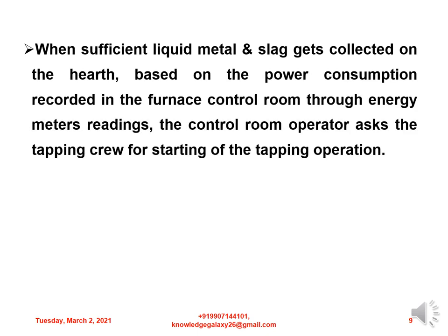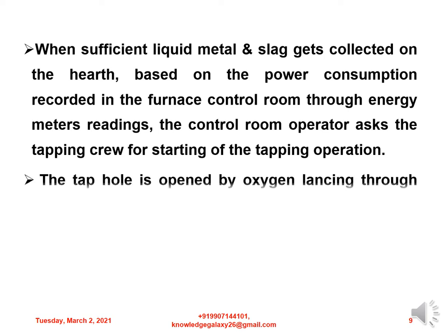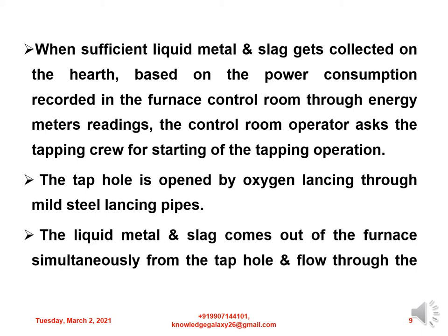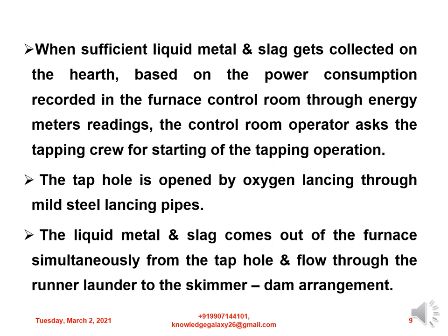When sufficient liquid metal and slag gets collected on the hearth — based on the power consumption recorded in the furnace control room through energy meter readings — the control room operator asks the tapping crew to start the tapping operation. The tap hole is opened by oxygen lancing through mild steel lancing pipes. The liquid metal and slag come out of the furnace simultaneously from the tap hole and flow through the runner and launder to the skimmer dam arrangement.